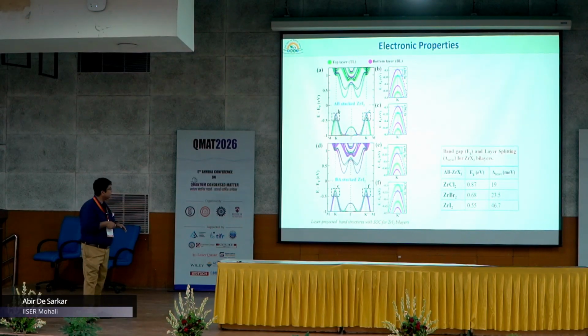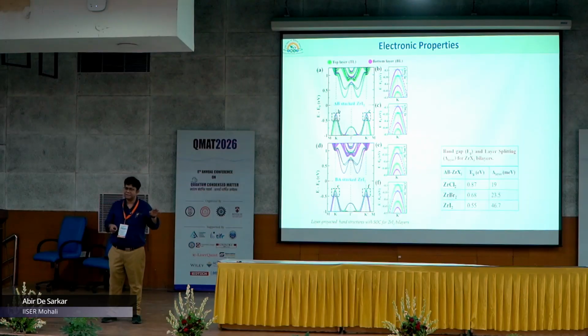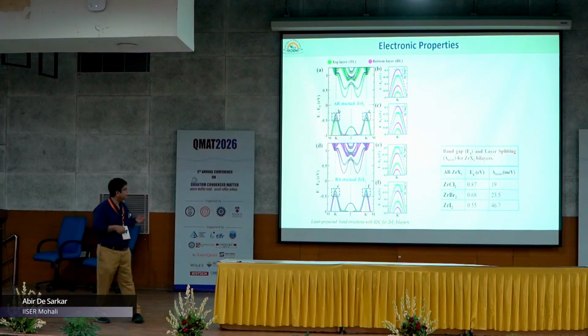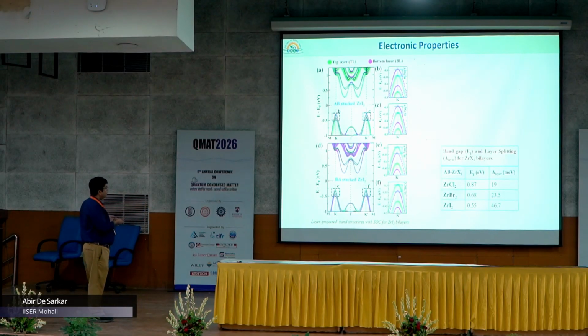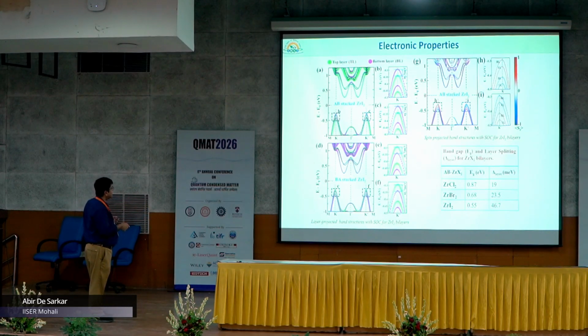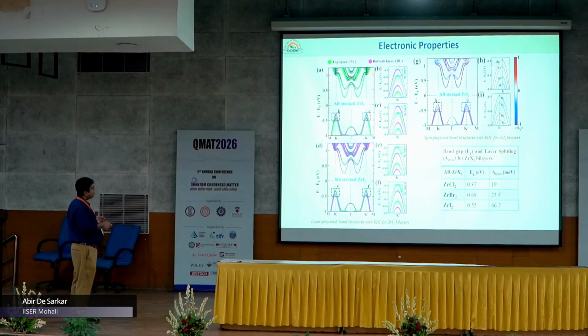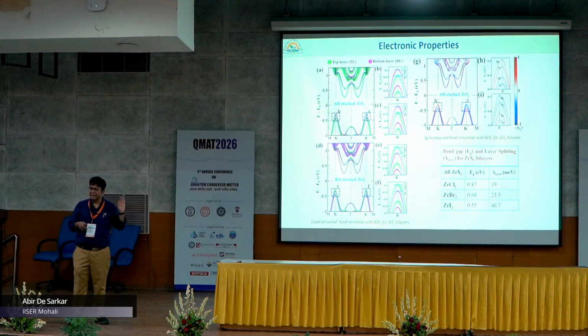And also, since the inversion symmetry is broken in the xy plane of these monolayers, they also show valley polarization, that is, opposite spins are found to be locked to the momentum valleys K and K prime. And what we find is that in this AB stacking sequence, the top of the valence band comes from the bottom layer, and in the other stacking sequence, the top of the valence band comes from the top layer. So layer can be a degree of freedom in this bilayer.